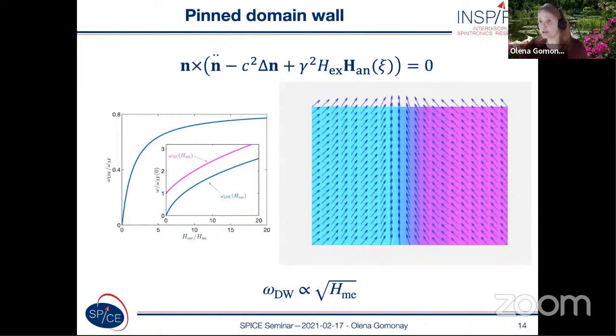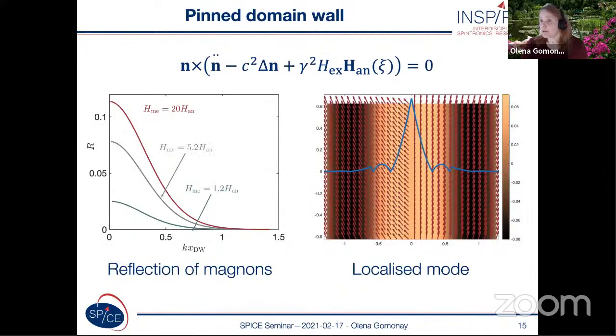So the domain wall in this case can be considered as a localized excitation which should be added into the magnon spectra. And this localized domain wall can also modify the dynamics of magnons. For example, it can induce a strong reflection of the magnons from the domain wall, as shown in the left panel. So the higher the magnetoelastic constant is, the larger is the reflection coefficient.